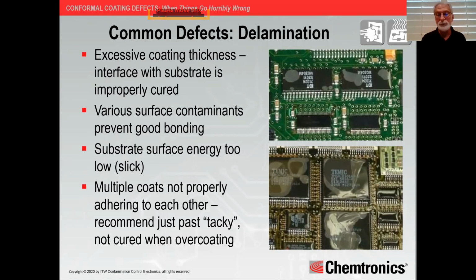Various surface contaminants can prevent good bonding. If you have a little silicone on there, maybe you've got a part that's a peel off that's stuck on there, any of those can prevent good bonding. If the substrate energy is too low, number one, it's going to feel very slick. Just on a bare board, it's going to be extremely slick. If it's lower than the surface tension of that coating, it can cause delamination. Now, what it's going to look like is it's going to look good. It's going to look like it's bonded to that surface. But 6 months down the line, it's going to pop up. That adhesion is going to fail.